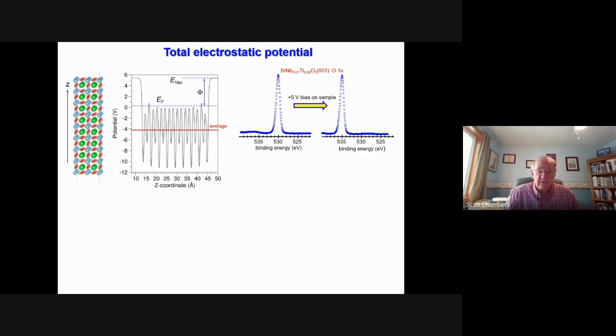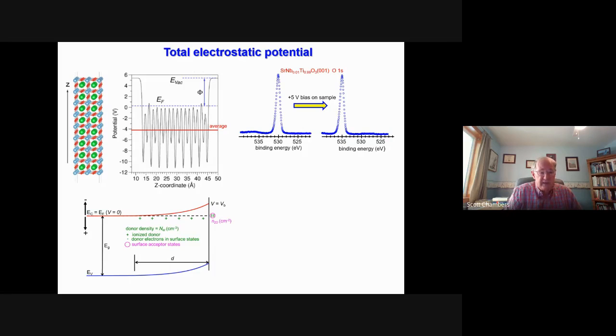Well, you might say, okay, that's great, but so what? Well, the point is that in semiconducting materials, depending on the electronic structure, there can be natural internal intrinsic forces that change the electrostatic potential. For instance, band bending in semiconductors. Okay, let's take an N-type semiconductor as an example here. And let's just suppose that you have some acceptor states on the surface. Well, those things can grab electrons from the subsurface region and charge up, leaving behind a positive space charge region down to some depth d, and that's going to cause all the electron orbital energies to shift up. Conduction band, valence band, and the cores are all going to move up.